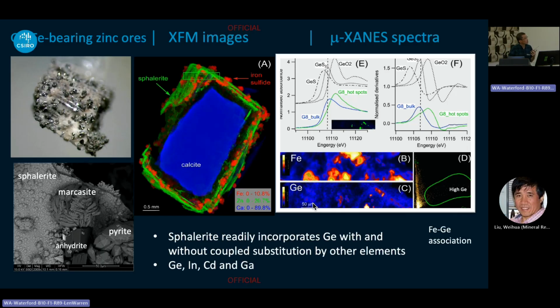So the simple version of how to do that: we measure the experimental sample, measure the natural sample from the deposits, and we compare the results for germanium. What is really shown is that germanium in the sphalerite is all in the germanium-4 plus state in those phases, regardless of what kind of germanium solution is in the water.